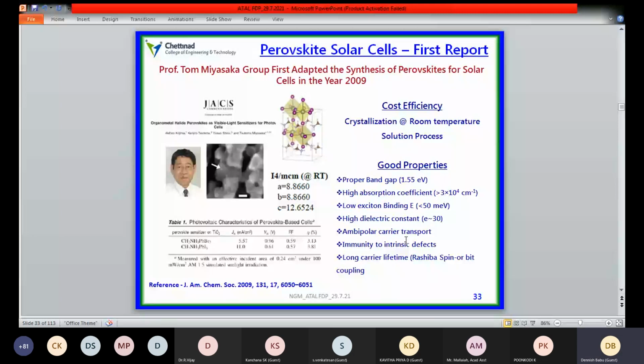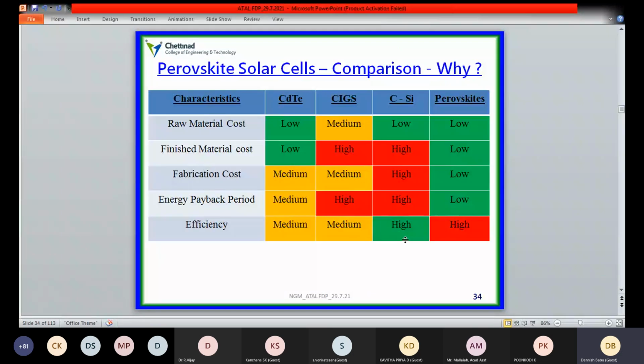So when we compare the perovskite-based systems with other already available solar cell materials, this is the comparison made with cadmium telluride, copper indium gallium selenide, and crystalline silicon based material systems. The raw material cost is very low, and the finished material cost is also very low compared to the other materials. The important one is that the efficiency is very much higher than the other materials. So this is the most important aspect to look at in perovskite-based systems for future electronic devices.